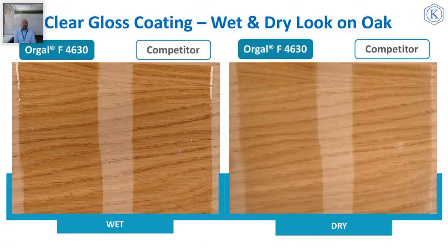We have tested film clarity and wood firing properties on 3 different wood types. Our first testing wood was oak. Those pictures are applicator drawdowns by 200 micron wet film thickness. On the left-hand side, the wet appearance of the clear top coat formulation just after applicator drawdown is seen. And on the right-hand side, film aspects after drying are shown. Orgal F4630 shows no whitish aspect in wet state and has excellent wood firing after drying.